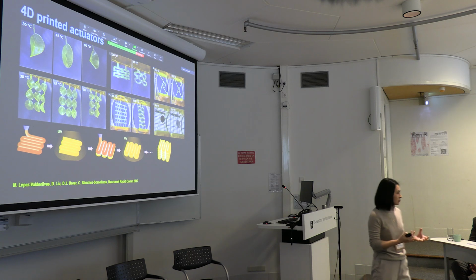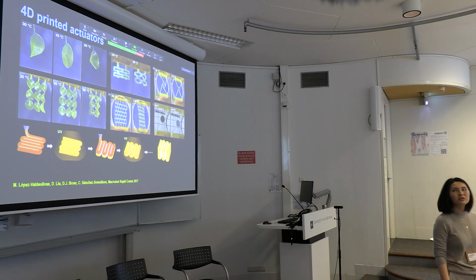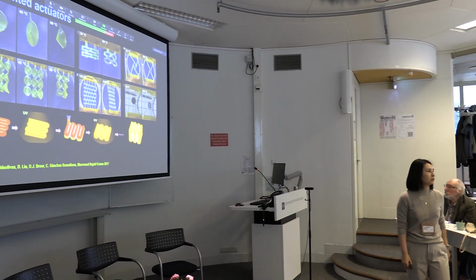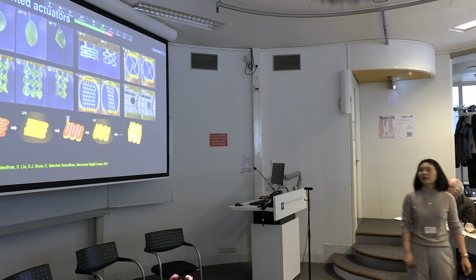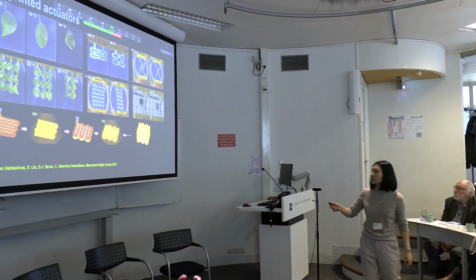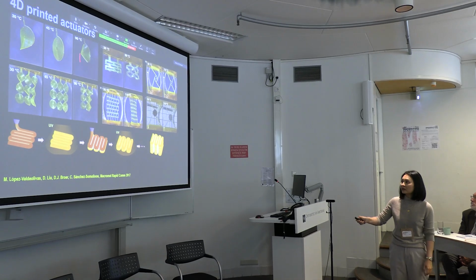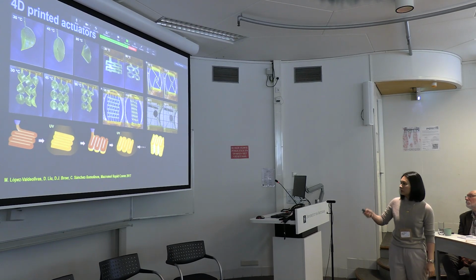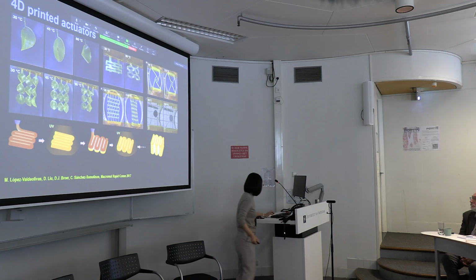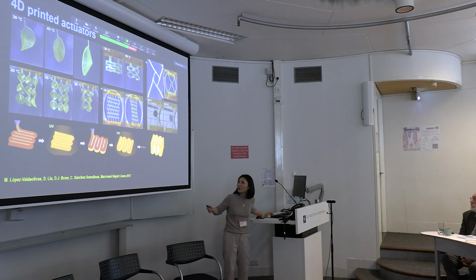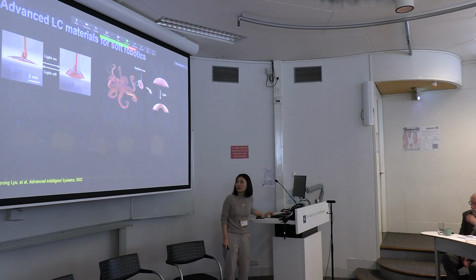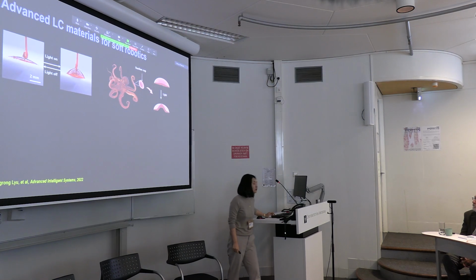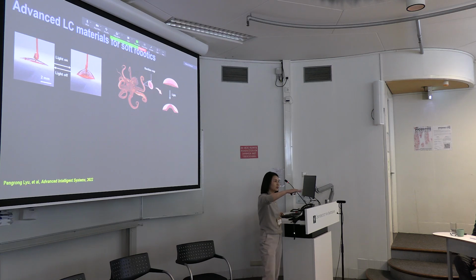Now, since this molecular architecture is tunable in height, you can figure out many ways of how you can manipulate the molecular structure, and then start to play around with different structures. Here you can go from flat to a cone shape, like you can see here. And for example, you can make a wheel out of that, and all different kinds of deformation we can imagine. One thing we find interesting is that we can make the substrate go from flat to cone-like, or the other way around, like you can see here.